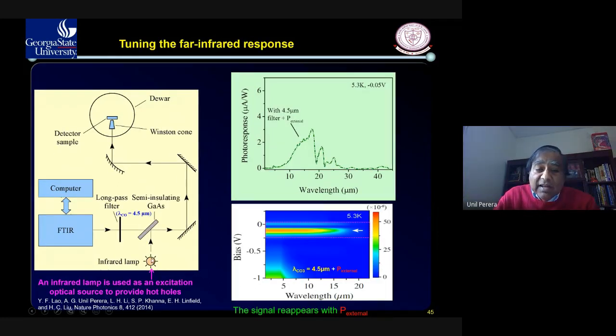But now when we send light outside, not from the FTIR, back again, we get the signal back. So this tells us that we need the incoming short wavelength to get to the long wavelength. So this is one way to detect far infrared without changing the energy gap, because the standard measurement technique for infrared detector is energy gap determines the wavelength threshold. The shorter the energy gap, you can go to longer wavelength. But when you reduce the energy gap, thermal effects come into play. So your dark current is high. So you need to cool it down.